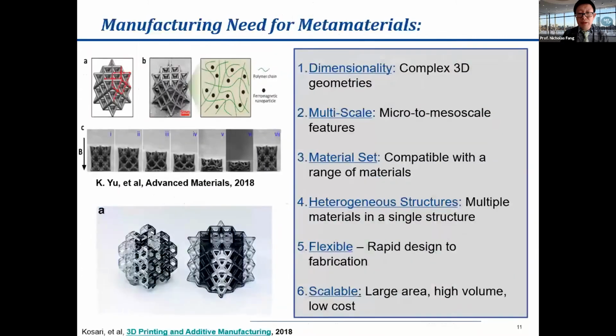With that, let me switch gears and talk about the manufacturing challenges that we are encountering in this particular domain. So we heard in the earlier talks that there are different needs, for example, for photonics and RF functionalities. Very often those are made possible by, for example, embedding metallic components or conductive species. And in the case of increasing magnetic permeability, then very often you will need to embed, for example, oxide materials, or even garnet type of special substrate. And we are looking at very different features. Some of those are responsible for heat conduction. Some of them are responsible, for example, for tuning the thermal capacity and conductivity.